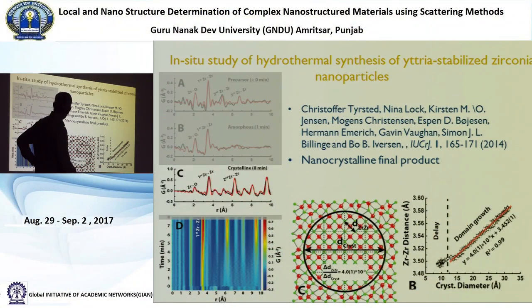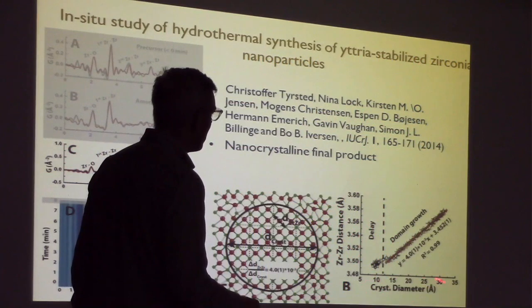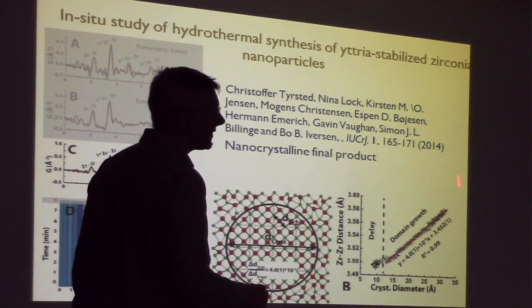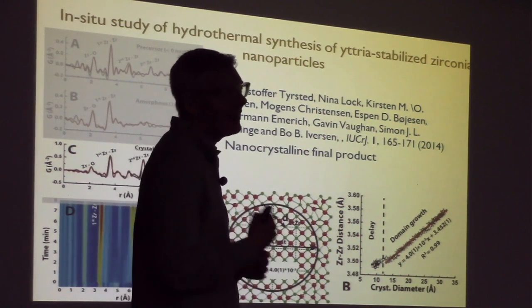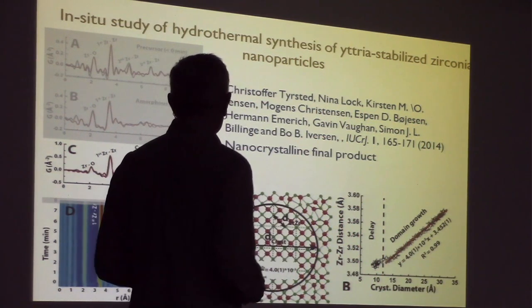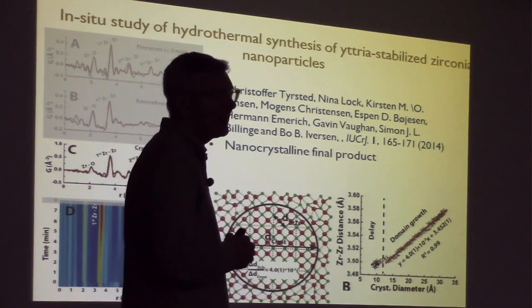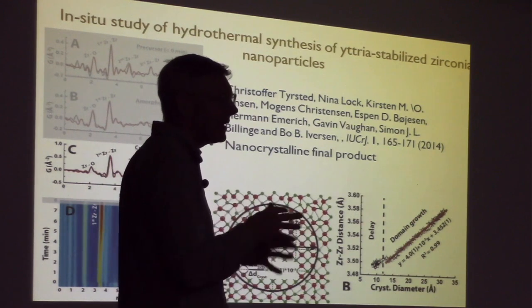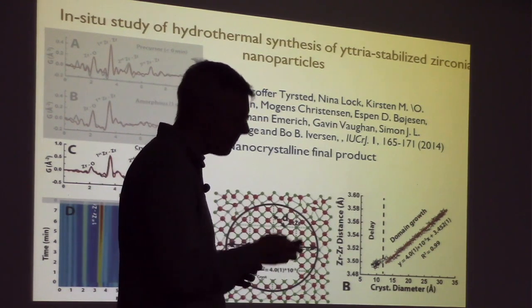And then finally, a little bit later here, you see these peaks start coming up, and the thing is producing the product, the yttria-stabilized zirconia. So some kind of crystalline material is forming in the middle of the amorphous material, and it's growing out. And there's some chemistry that we can get, so we can look at the zirconium distance as a function of the diameter of the crystallite, and we see that it's changing continuously like that. So there's some chemistry going on at the same time as this thing is recrystallizing. And I'm not a chemist, so I don't really understand the significance of that. But it's just showing you the kind of detailed information that we can get about synthesis happening in real time.